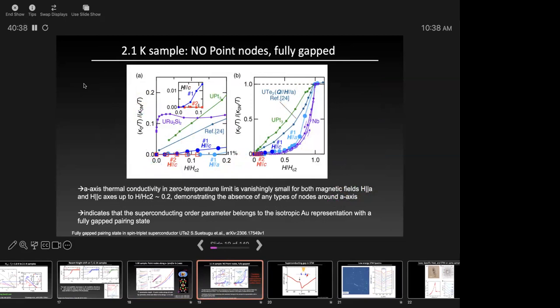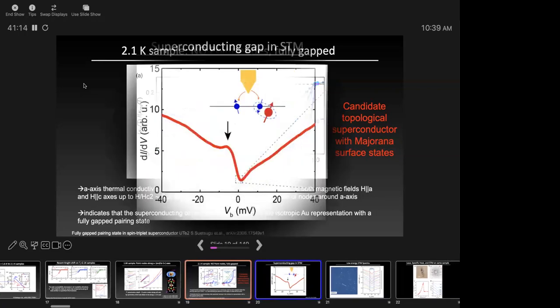So it's a fully gapped superconductor, which actually is, if you look at all the possible order parameters, there is one that would be consistent with a topological superconductor. We haven't discovered any of these. It would be pretty nice. I would be happy if this were a true 3D topological superconductor. It might even explain what we see on the surface. But like I said, this is just one experiment, and we should be careful about jumping to conclusions. Yes.